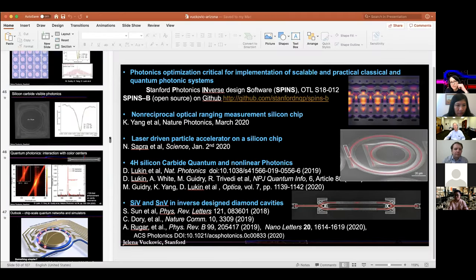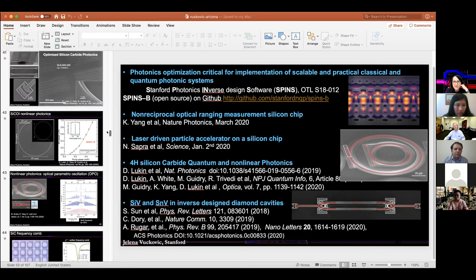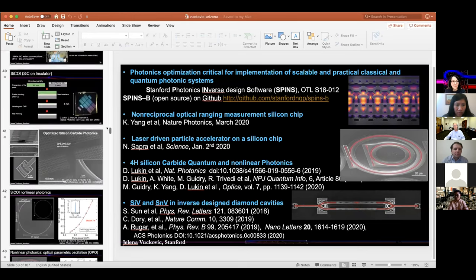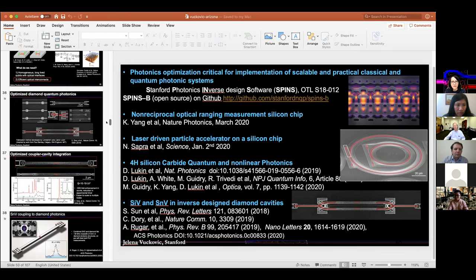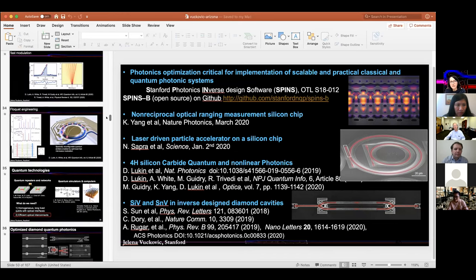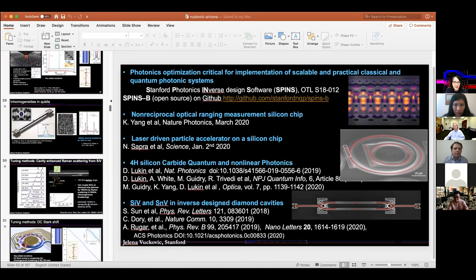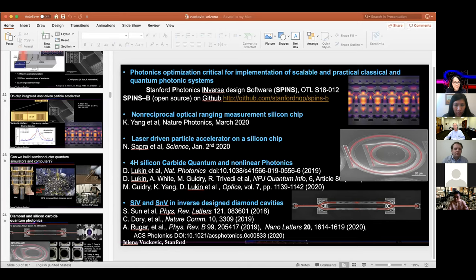The paper itself, which we published in Science about a year ago, has a detailed analysis of everything that is going on there. But the short answer is that in this particular experiment, we didn't really bunch the electrons. We generate them with 300 femtosecond laser pulses from the tip, right? So they are not really bunched and they're not synchronized with the electric field of the structure. I mean, they're synchronized up to a certain level, but not completely, which is why when you're looking at the experimental results here, that I'll just show again, here it is.